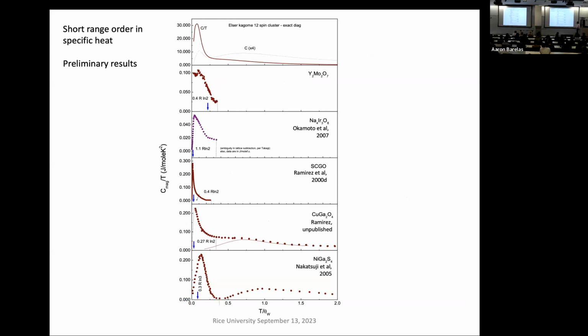The only one for which we have really good specific heat data is nickel gallium sulfide, primarily because its Weiss temperature is only 100 degrees. All the others have much higher Weiss temperatures. So Nakatsuji measured this, thank goodness, and he gets almost all the entropy in two peaks, one around Weiss theta and one around this low energy, this hidden energy. So this isn't even the whole story. There's a lot of entropy loss.